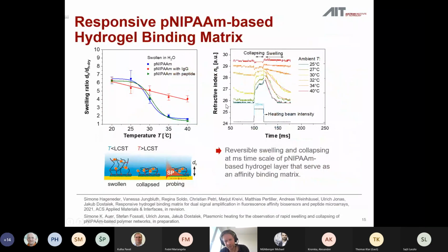And in the last two slides, I'd like to address this possibility of using responsive hydrogel architectures. In this case, we thought to use the hydrogel matrix, which in the open, swollen state allows capturing the target analyte, which can efficiently diffuse through the structure, and then trigger the collapse, in this case by temperature, and compact the captured analyte on the surface, and then probe it more efficiently. This triggering of the collapse could be done for this N-isopropylacrylamide, so-called NIPAM based hydrogel, by temperature changes around 30 degrees. And indeed, the system responds relatively fast, in the millisecond time range, as we saw in another study.